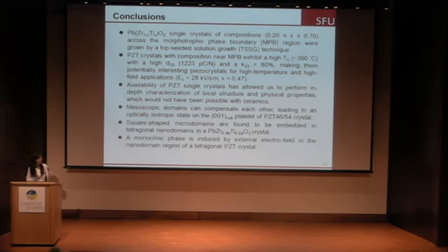To wrap up my presentation, in this work, we've grown PZT single crystals with compositions from 20% to 70% PT, and the best piezoelectric constant we obtained is 1223 pC/N with a k33 value of 80%. And this makes the PZT single crystal a potentially interesting piezo crystal for high temperature and high field applications.